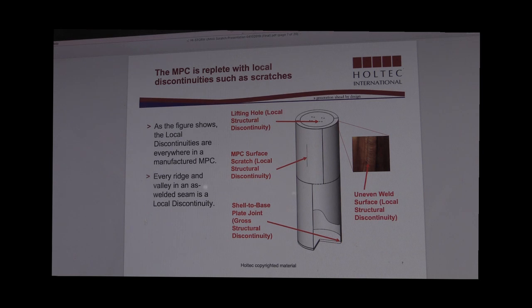One example would be the small lifting holes that are in the MPC lid, which are used to handle the lid as well as the MPC. And even if you think about the lid to shell weld, which is part of the containment boundary, that closure weld, even at the surface of that weld, which hopefully you can see in the close-up photo there, it's quite uneven, and there's numerous ridges and undulations in that surface. So even those irregularities in the weld would be examples of local structural discontinuities, as well as any surface scratches on the MPC. So the point that we want to make here is that local structural discontinuities are quite prevalent on the MPC canister in many different forms, and scratches on the surface is just one obvious example of a local structural discontinuity.